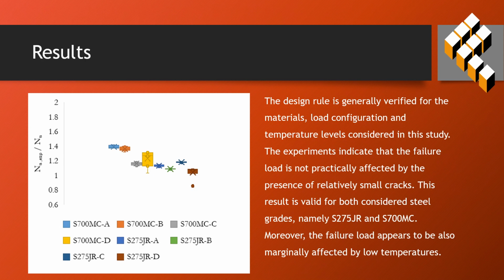The experiments indicate that the failure load is not practically affected by the presence of relatively small cracks, generally smaller than 1 mm. This result is valid for both considered steel grades, namely S275 and S700. Moreover, the failure load appears to be also marginally affected by low temperatures, close to 0 Celsius.